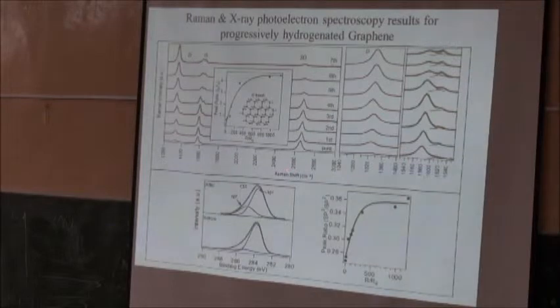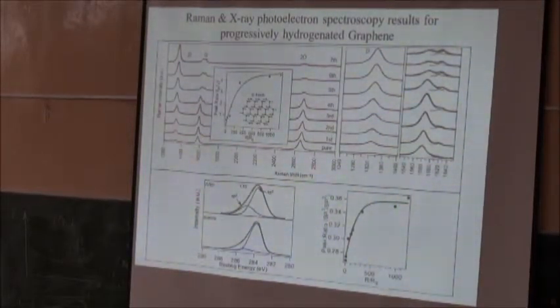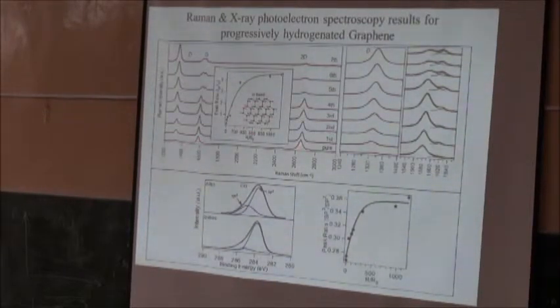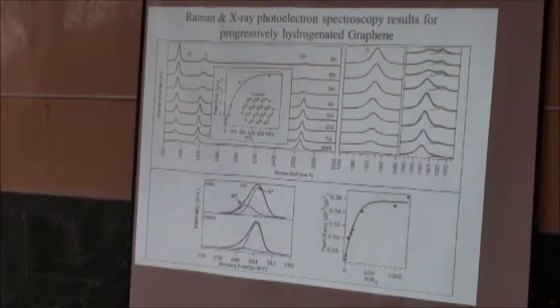This is always present. This is actually a two-phonon process. So you can see this is the signature of good graphene. You have the D band, the G band, that's this vibration. We call this the 2D band. Okay, so you have a very nice picture here.